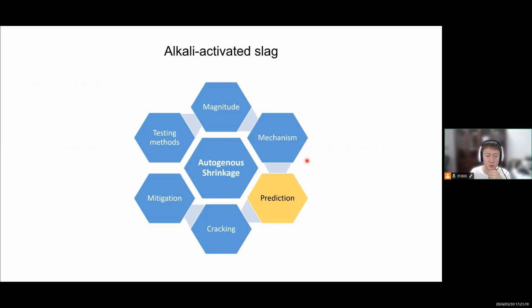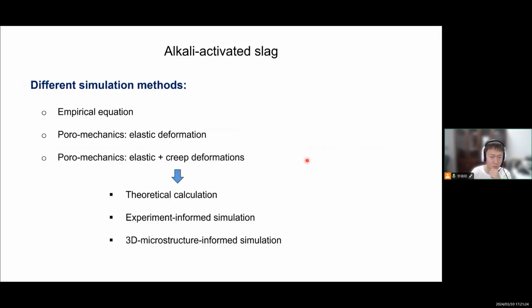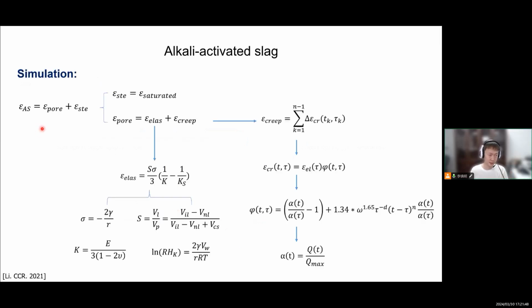And since we know the mechanisms already, we should be able to predict the shrinkage. There are a lot of types of models available, but because we do not have a 3D microstructure-informed model to predict shrinkage of alkali-activated materials yet, I used a method which is half theoretical and half experimental. There are even empirical parameters. So I divided the shrinkage into two parts. As we found, part of the shrinkage is caused by the pore pressure, capillary pressure, but another part is the steric hydration force part.